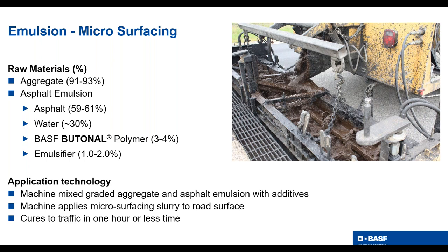The technology in getting this mix down is, and you'll see on a few pictures later, that this is machine mixed with a graded aggregate. So asphalt emulsion goes in along with usually some water and some additives, whether it's some fine cement to trigger the reaction or some additives even to slow down the mix at times in warmer climates. The machine then applies this microsurfacing as a slurry to the road surface. And the key to microsurfacing is that it cures in traffic in 1 hour or less time. And this is very important in some of the pictures that I'll show you.